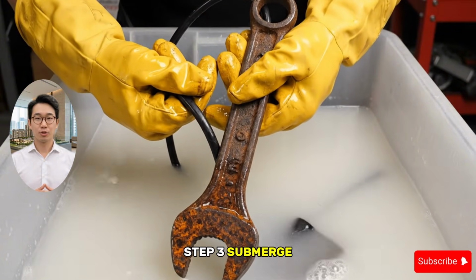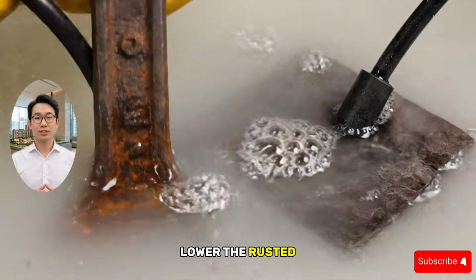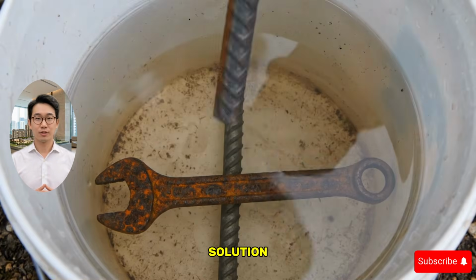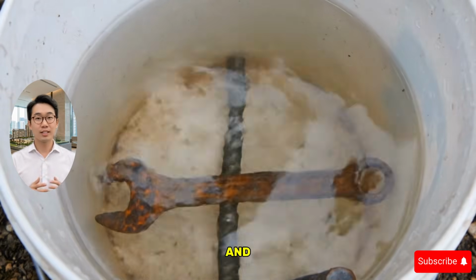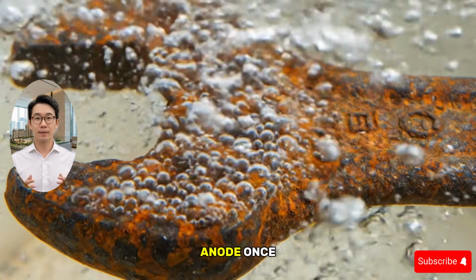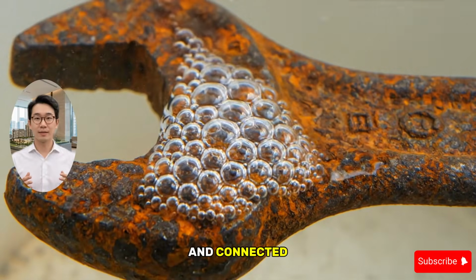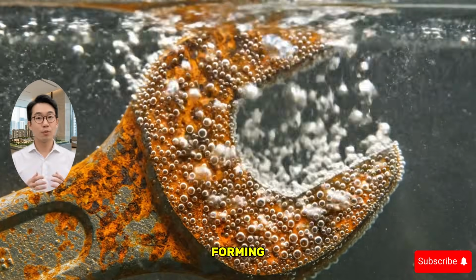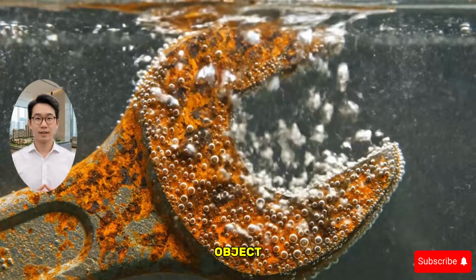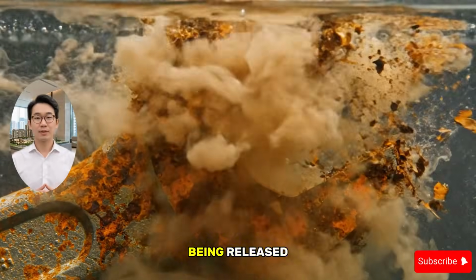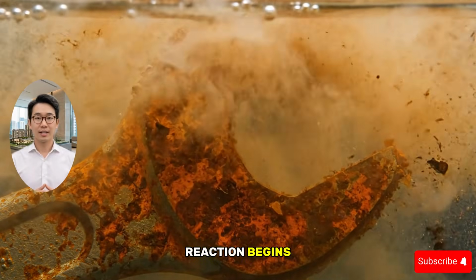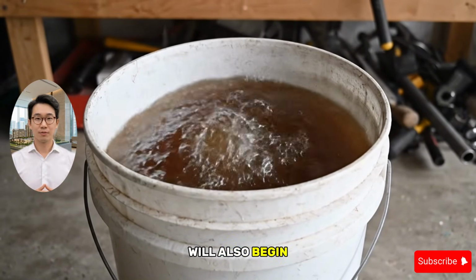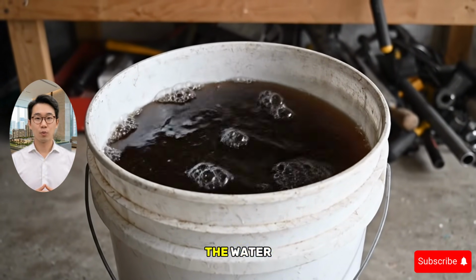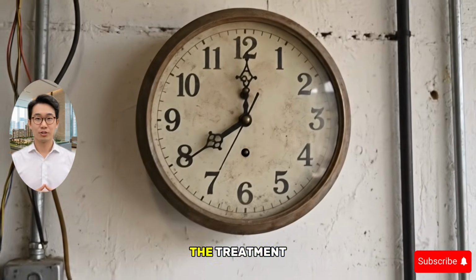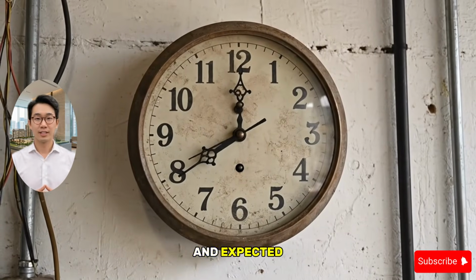Step 3. Submerge the rusted object. Lower the rusted object into the electrolyte solution, ensuring it is fully submerged and not touching the sacrificial anode. Once both are submerged and connected, you will immediately see small bubbles forming on the surface of the rusted object. Those bubbles are hydrogen gas being released as the electrolysis reaction begins. The rust will also begin releasing into the solution, turning the water progressively darker brown as the treatment proceeds. This is correct and expected.